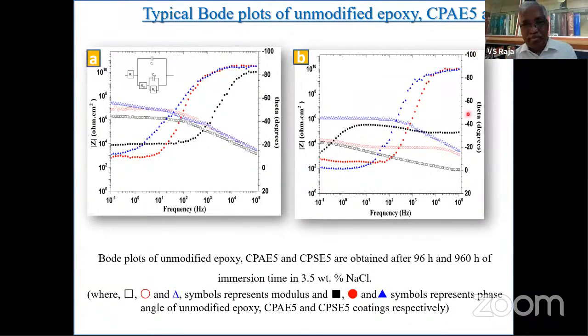And again, you can see how by modifying this, through systematic work, various proportions of these additives are being added, and then the corrosion resistance is being determined in this case. Okay, so again, these are the plots of unmodified epoxies and epoxies modified with these two additives. Please look at this: after about 1,000 hours of exposure, you still have 10 power 6 impedance. That means it's really good.